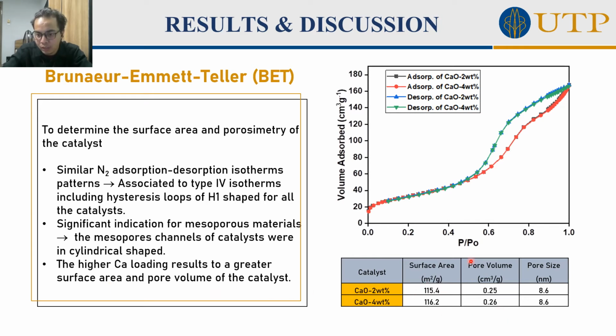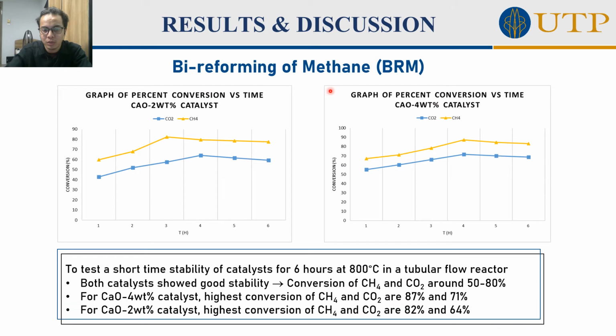So we can refer to the table here. For the surface area, the CaO 2% is around 115.4 square meters per gram, and for 4% it is 116.2, which is slightly higher compared to 2%. For the pore volume, the same thing happened, where 4% is higher, which is 0.26, compared to 2%, which is 0.25. So we can conclude that the higher the loading of Ca, the greater the surface area and also the pore volume of the catalyst. So proceed to the next one, which is our main objective for this project, bi-reforming of methane for our catalytic testing.